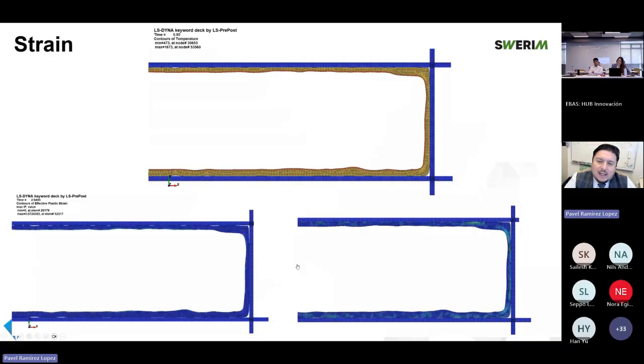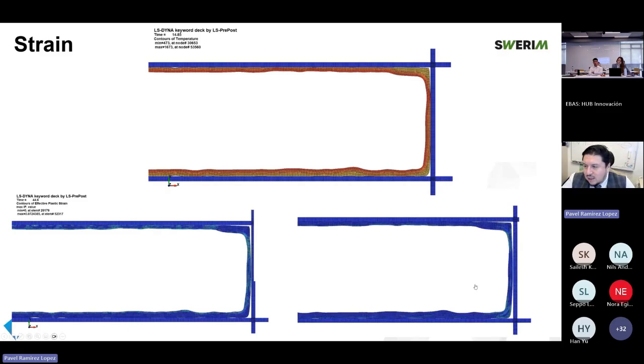What we get is a very interesting simulation where, for a given shell, we can observe the evolution of the stresses as they progress. Of course, you need to think about it in a reverse way, but at the end of the day, what we are trying to understand here is the tapering conditions of the mold against the shell, and whenever we lose contact. So you see here very clearly in some sections how we lose contact with the narrow face and what this generates, which is the separation of the tip from the wall.